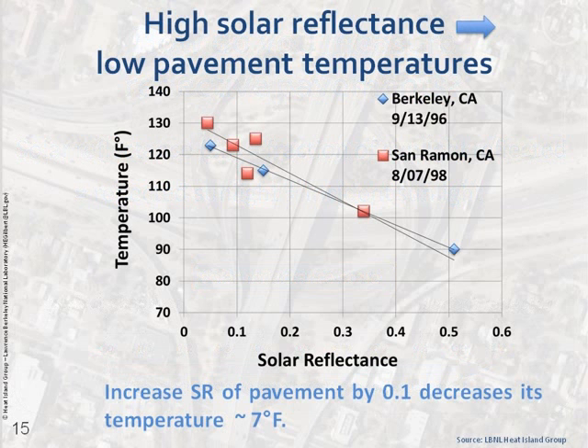And simply put, the more reflective a pavement surface is, the lower the pavement temperatures get. So here you see from several contexts the relationship between solar reflectance and surface temperature. And you can see that as you increase solar reflectance by about 10%, you can actually decrease its surface temperature on the order of 7 degrees Fahrenheit. So it makes a big difference. And the cooler the surface is, the cooler the air around the surface will stay as well.